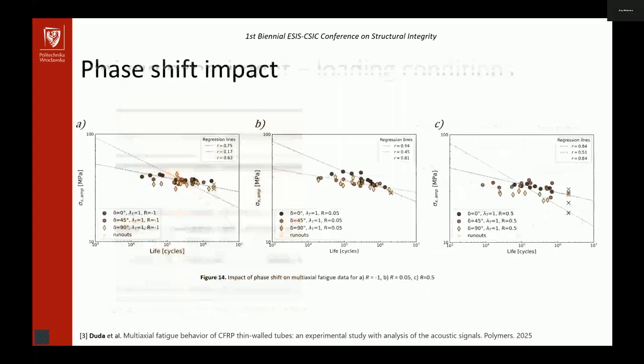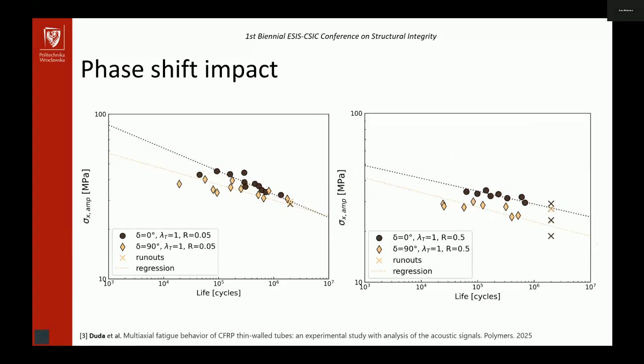And so you can see the results, and in some cases, in this form, we cannot really say what the impact of the phase shifts is. Why? Because due to the low correlation in some cases, the effect is hidden. That's why, if we think only about the positive R ratio, where there is no compression, which might cause additional challenges such as local buckling of the fibers, we can see the effect of 90 degrees out-of-phase loading.